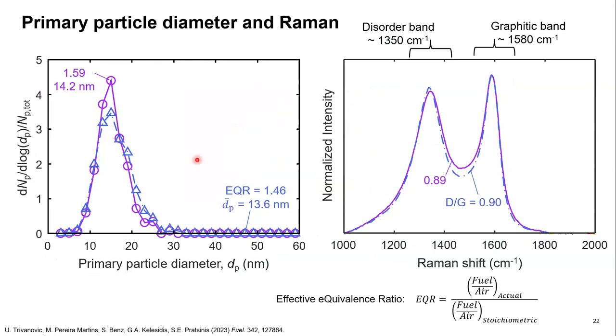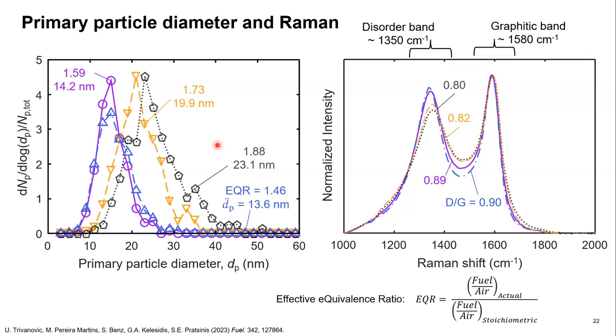So as we showed before, the primary particle diameter at the relatively lean equivalence ratios was nearly identical for equivalence ratio 1.46 and 1.59. Similarly, the Raman spectra were also nearly indistinguishable. However, if we go to much richer conditions of 1.73 and 1.88, we are able to shift to larger primary particle diameters up to 23 nanometers. And at the same time, the Raman spectra show a decrease in the D to G ratio down to 0.8 at the richest equivalence ratio. And this suggests that the particles are more graphitic. So what we see is that high equivalence ratios lead to larger primary particles that are more graphitic.